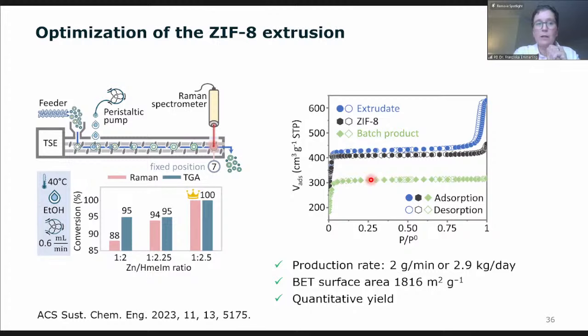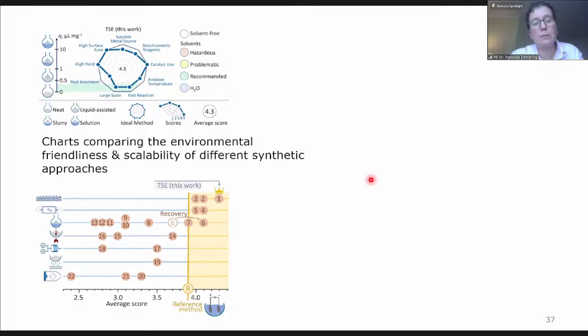Okay. But as I said at the beginning, mechanochemistry also always claims to be the green method, and we should also be able to prove that. And therefore, we come up with these radar charts, checking the different synthesis techniques that are out there for ZIF-8. There are around about 30 different ways you can synthesize ZIF-8, and you see here a comparison, and you can also see the parameters we looked for.